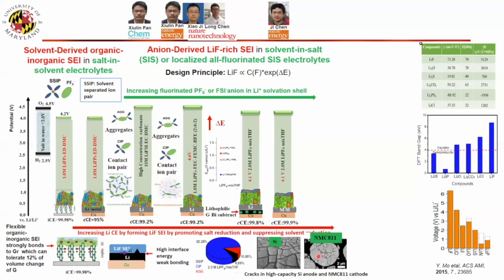And right now, everybody wants to use a high capacity cathode, NMC811. Whenever you have a high capacity, it will crack. The same principle holds if you form a lithium fluoride SEI. Even inside the crack, electrolytes cannot penetrate, and they can still achieve a very stable cycle life. So we'll show some data.